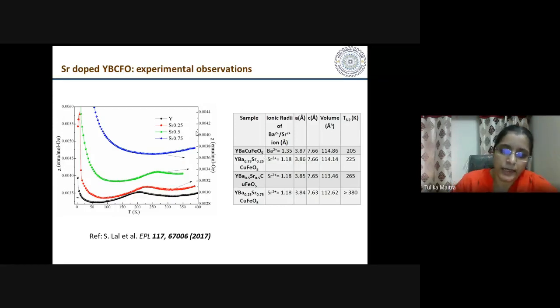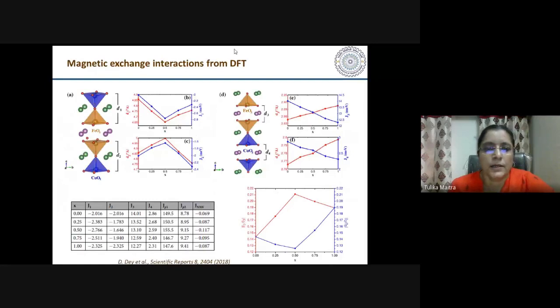So we also looked at the effect of this doping on the exchange interaction. So here we dope the system with strontium at various dopings: 0.25, 0.5, 0.75 and fully doped by strontium, and we calculated all the exchange interactions for various dopings, and we see that with doping it has a significant change.